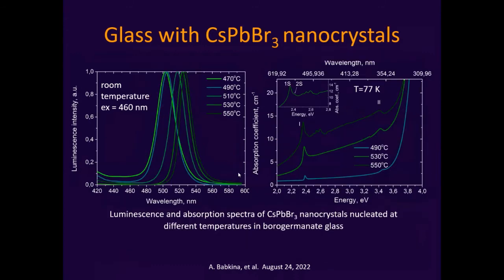What about bromide nanocrystals? Here, a very peculiar thing happened, because usually cesium lead bromide perovskite nanocrystals have the most intense luminescence compared with crystals with other halogens. But in our case, we obtained glass with these nanocrystals with a maximum quantum yield of 15%. So I think that in this case, we will work further to improve it.